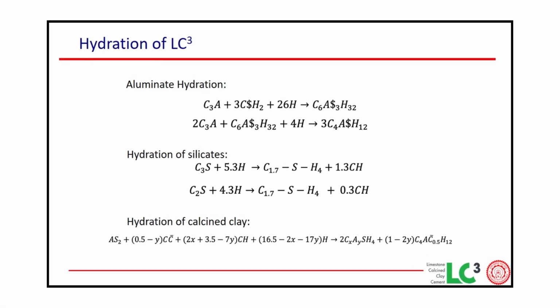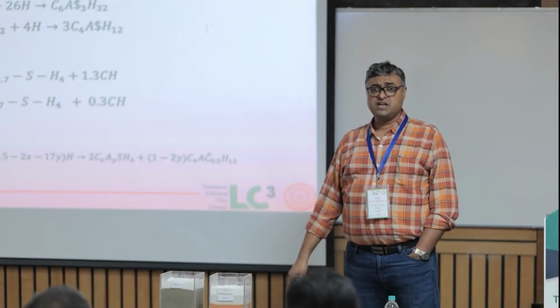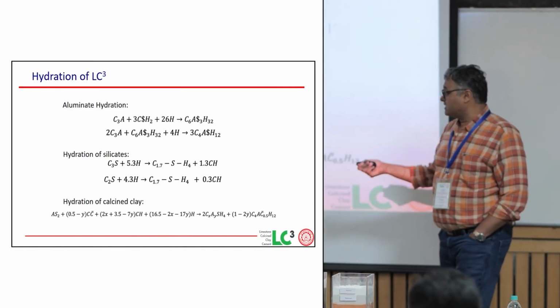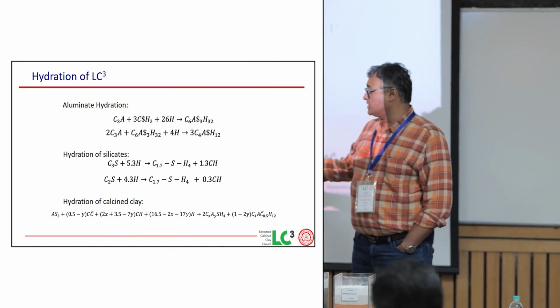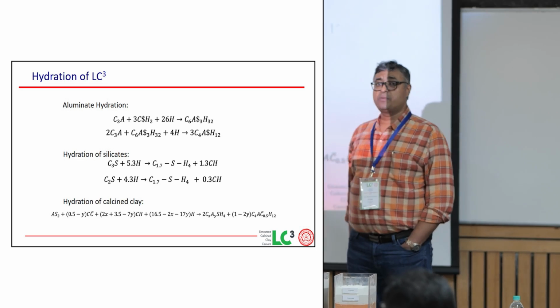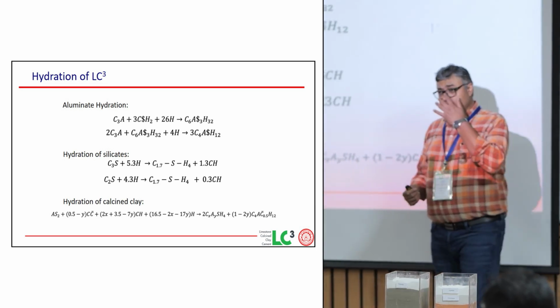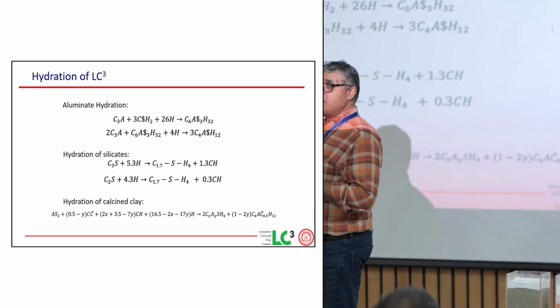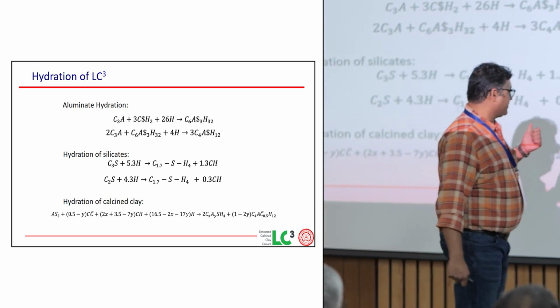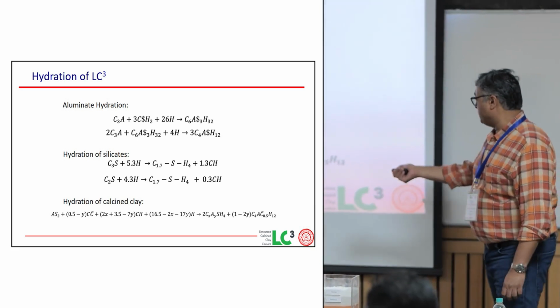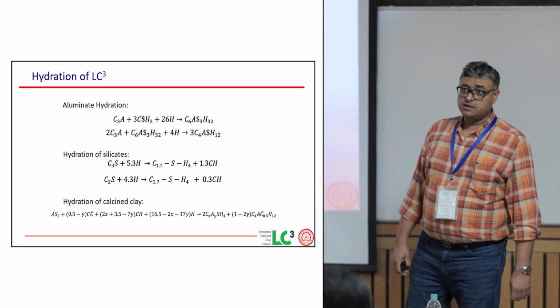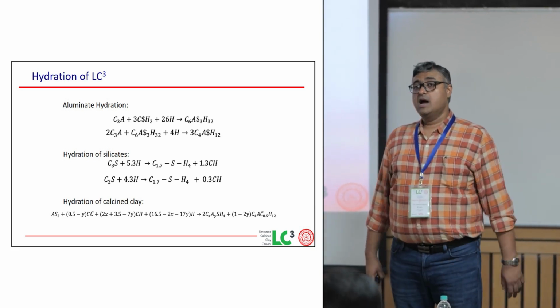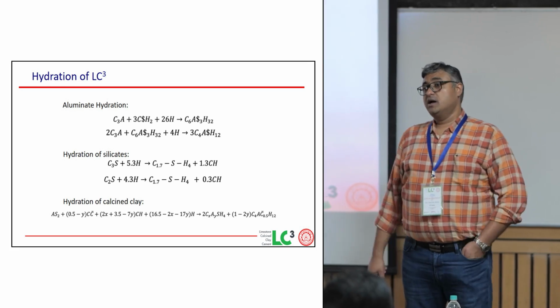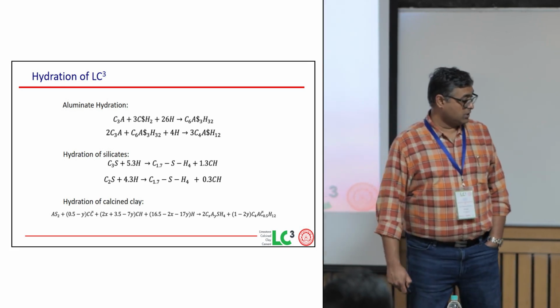What is happening is that in the clinker, you have various phases that are present. You know, there is alite, there is belite, they react with water, they produce calcium silicate hydrate, and they produce calcium hydroxide. This calcium hydroxide can now react not just with the clay, that is the aluminosilicate mentioned over here, but also the calcium carbonate, which is in the limestone. So limestone, which is otherwise usually an unreactive material in cement, starts to react, starts to produce carboaluminate phases that fill in the microstructure and give you better strength and better durability despite the lower clinker content in the cement. This is something we're going to see over time.